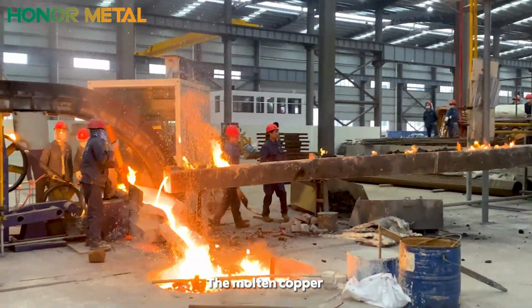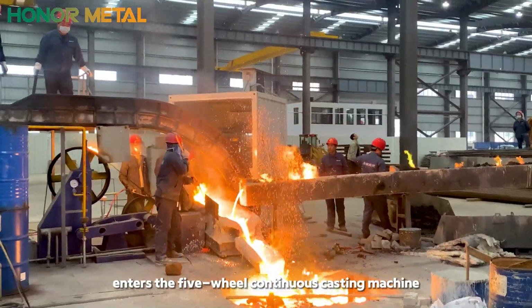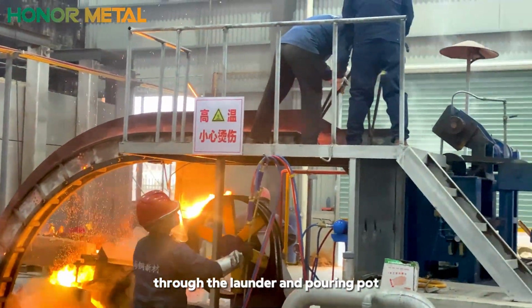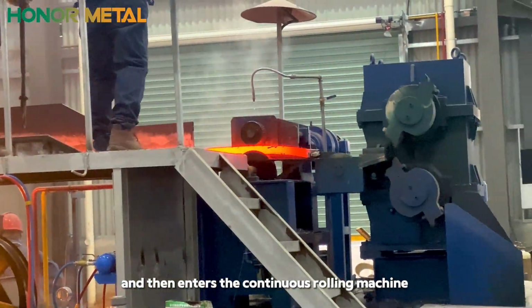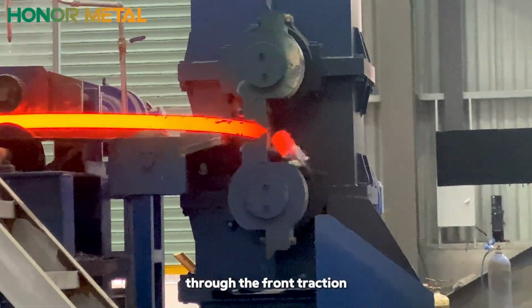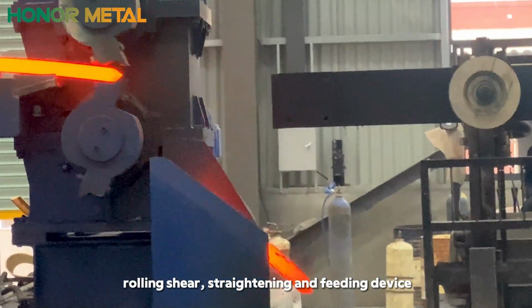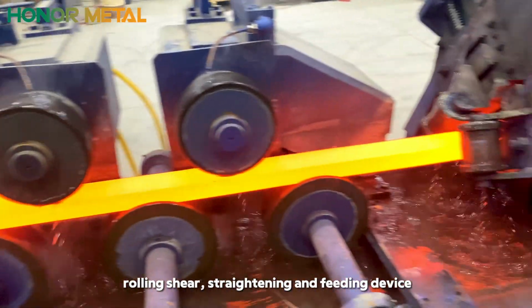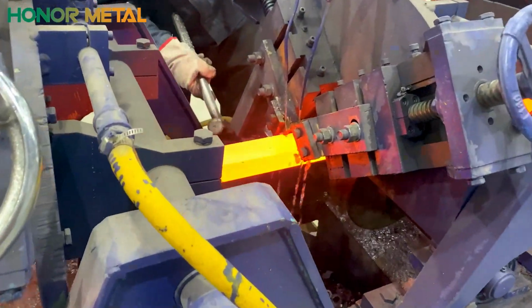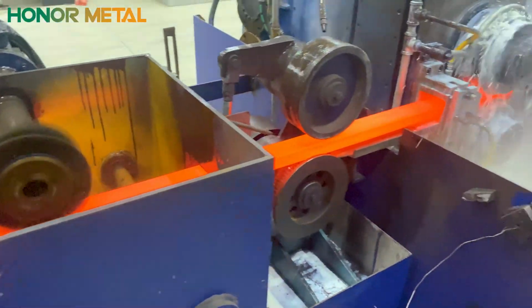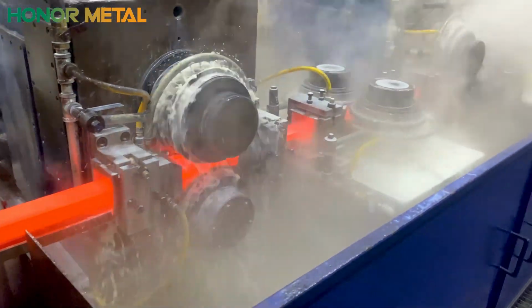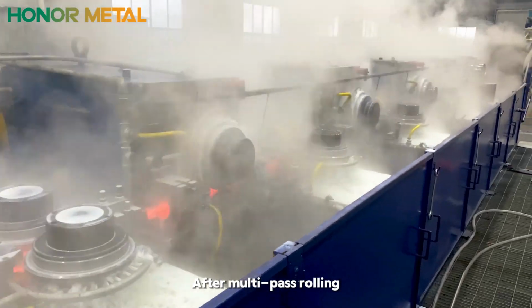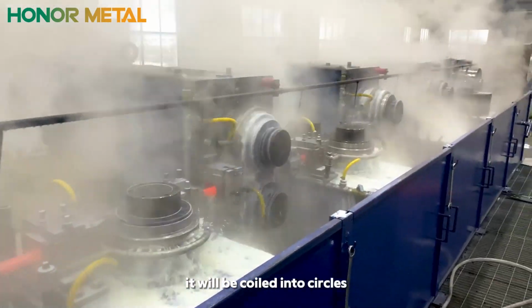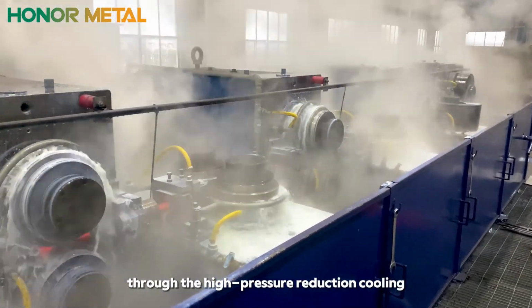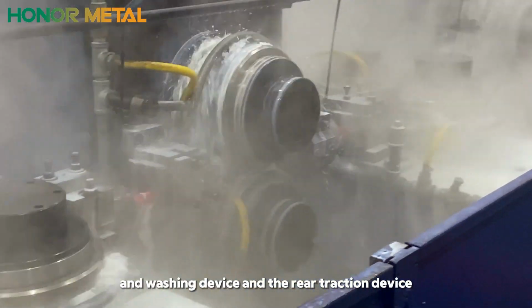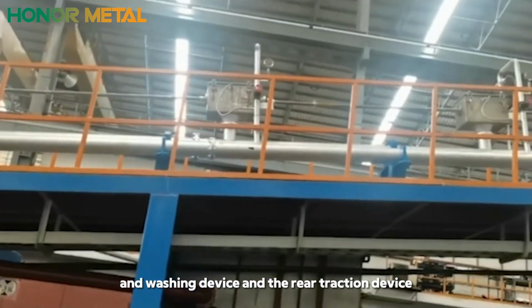The molten copper enters the 5-wheel continuous casting machine through the launder and pouring pot, and then enters the continuous rolling machine through the flat traction, rolling shear, straightening, and feeding device. After multi-pass rolling, it will be coiled into circles through the high-pressure reduction cooling and washing device and the rear traction device.